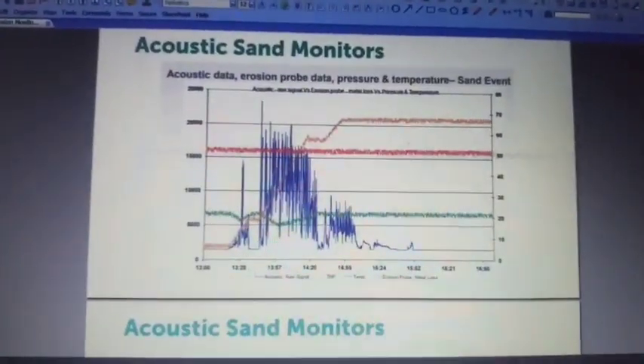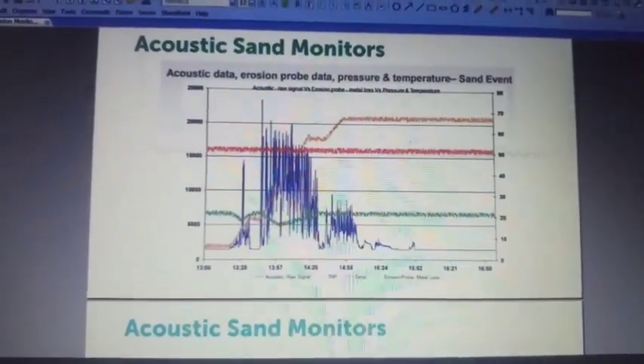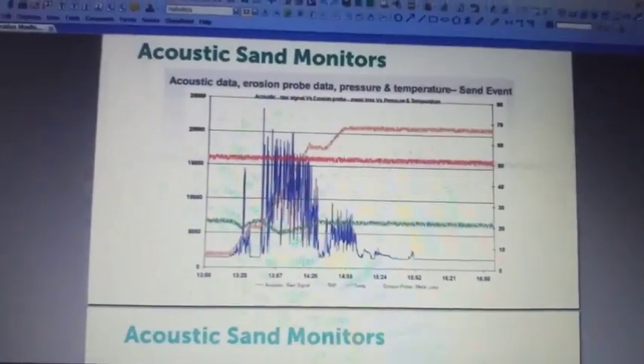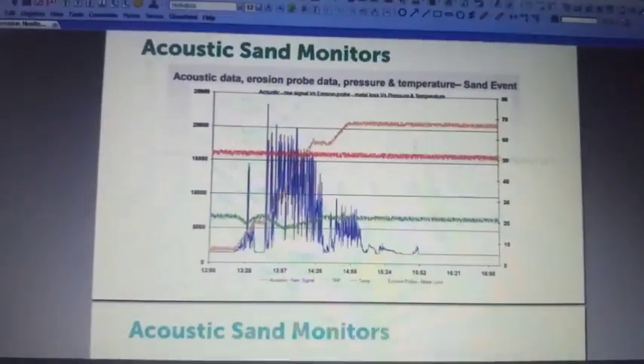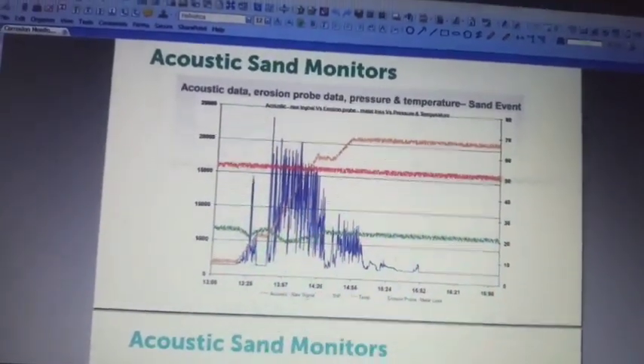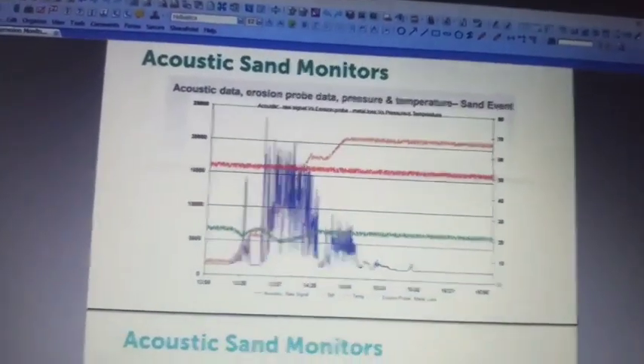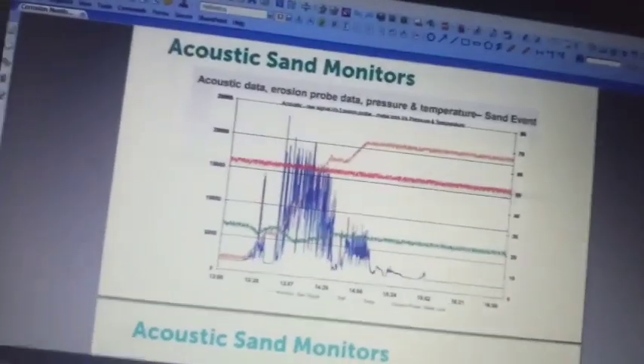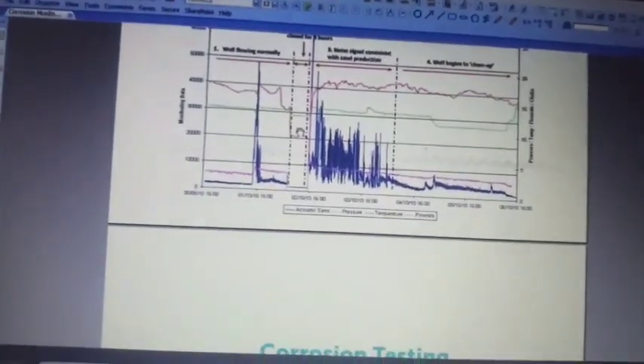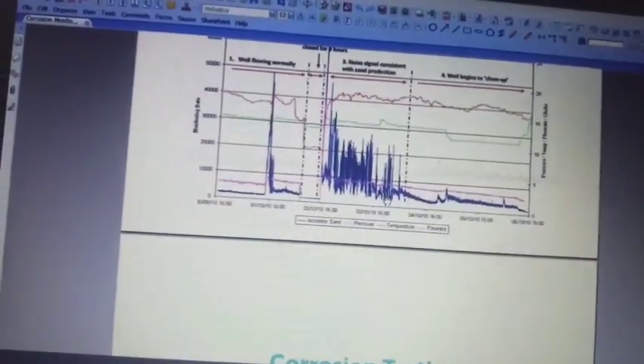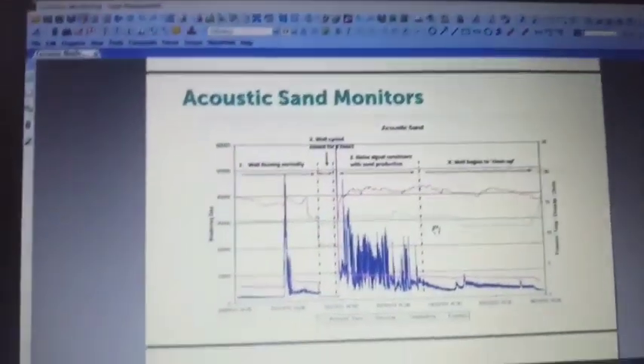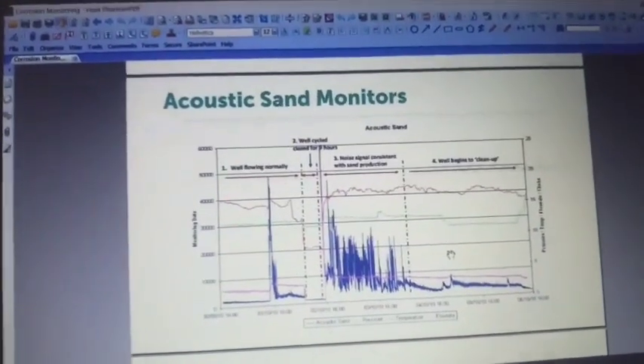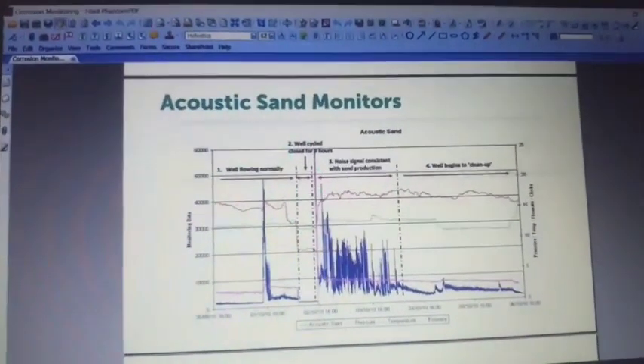Initially, there was some sand loading, so some minimum erosion rate jump, and then it is flat, and then there is a huge sand loading. Then there is a higher jump in the erosion rate because the sand loading is high, and the duration is also very high. And then there is a minimal sand loading for a shorter duration. Accordingly, the erosion rate jumped to a very small limit, and then it stayed. There is no sand loading after that, so the erosion rate is constant. You can see that? You can understand this graph? Yeah. So that's how it is.